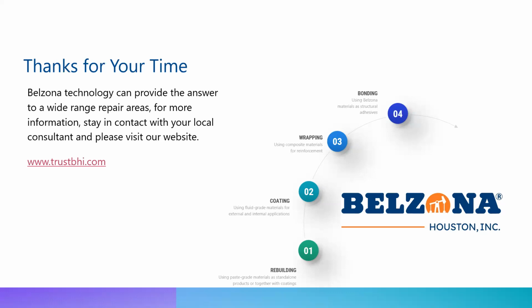Alex, do you test your chemicals at higher temperatures? Yeah, we'll test the resistance. So we have a chemical resistance chart where we'll have a variety of chemicals tested at different concentrations and temperatures. We test from 68 degrees to 194, and then we do some specialized testing above that as well. And if we don't have your chemical tested, we can always analyze to see what we have tested and what's comparable. And we have a good relationship with corporate, so they can get the R&D team behind it and look into the chemistry and find a good product for you.